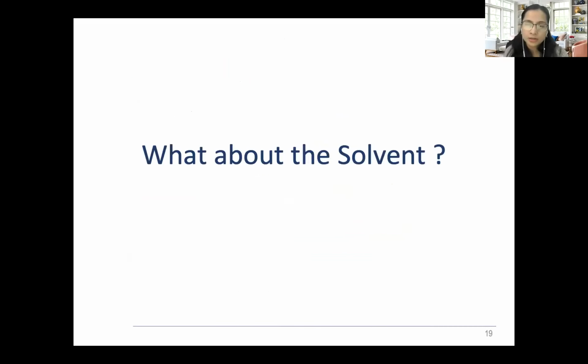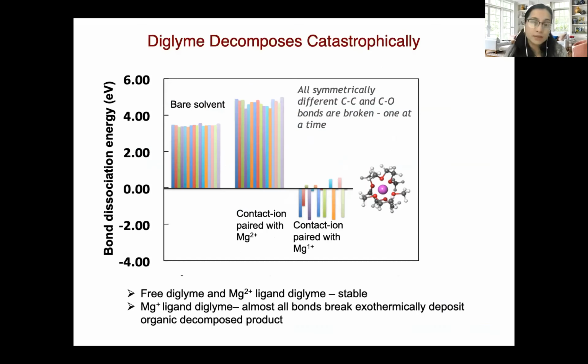And that brought our attention to the solvent, to what's happening to the solvent at these low concentrations. And we identified that at very low concentration, it's the solvent which is completely surrounding the cation, okay, and forming a very strong bonding. So we tested the chemical stability of the solvent. Again, we did it in 3 different chemical environments: the solvent by itself, solvent when paired with magnesium 2+, and the case when solvent is paired with magnesium 1+. And the solvent is pretty stable. It becomes actually more stable when paired with magnesium 2+. But you can see that pretty much all the bonds turn from being highly endothermic to highly exothermic when the solvent is paired with magnesium 1+.